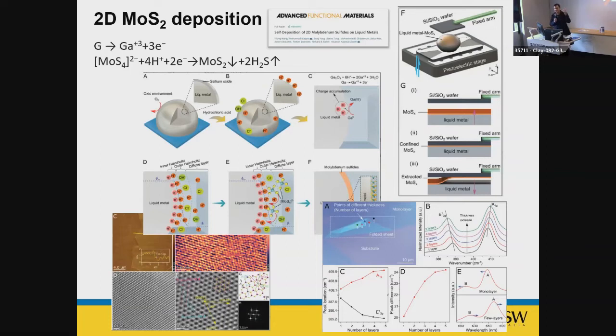This time we didn't use hand. It was very difficult. We used a machine stage that goes up and down, nano size, piezo stage, and we could go down to 1, 2, 3 millimeters, large areas. We're not talking about micron anymore. And as I say, single crystalline, very good quality, any layer thickness that we wanted to.